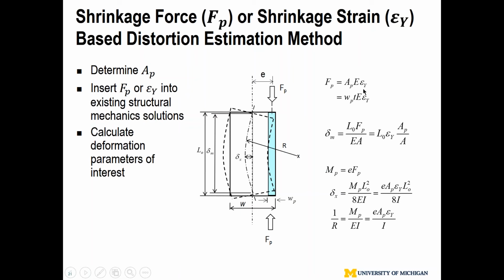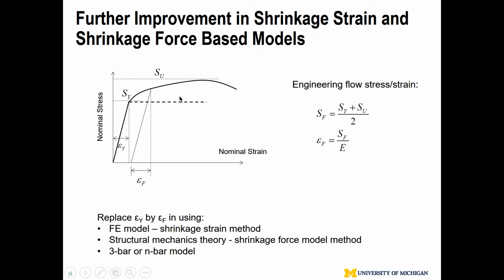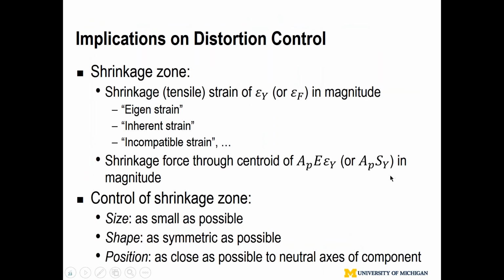Within that zone, the shrinkage force will be SY, that's the yield strength of the material, multiplied by the area, giving the shrinkage force. Once I know the shrinkage force, I can go to different structural mechanics solutions. Obviously, for this case, beam bending problems, I can go to, say, the average longitudinal shrinkage and also rotation of the beam, deflection, can all be calculated by structural mechanics principles. If it is a shell plate structure, you use shell plate theory. If you don't have an analytical solution available, you plug in the shrinkage force or shrinkage strain using a finite element model.